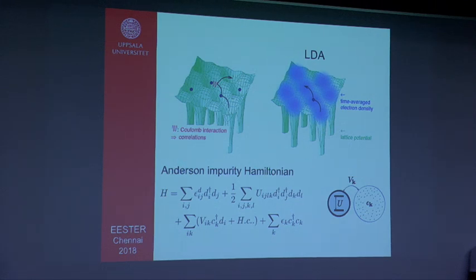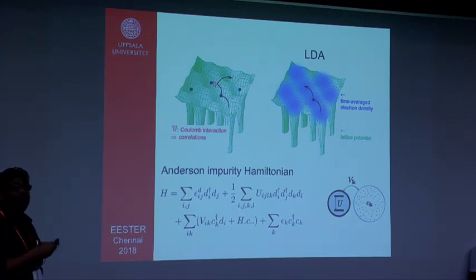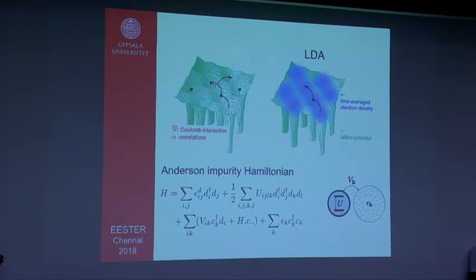And that is one of the ways to look into this: for the impurity, you take the Anderson impurity Hamiltonian for solving this impurity problem. It looks complicated here, but basically the first term is the on-site term of this impurity, the correlated levels. And then the next term is the Hubbard interaction, the U term here, and then you have the hybridization between this impurity and the bath states. That means it basically tells us the constant fluctuating exchange between this impurity and the bath. And this is the bath term, basically the kinetic energy in the bath electron system.